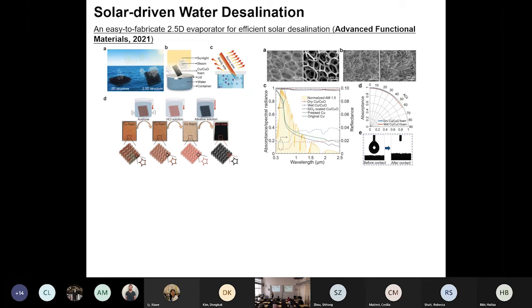So this material itself must be hydrophilic. So to do that, what is the concept? We found a way to oxidize the copper foam. So now we obtained oxidized copper foam, totally changed the color to dark, to black. Because in my research lab, we like black color. Why? Because black means blackbody, it's going to absorb most of the sunlight.